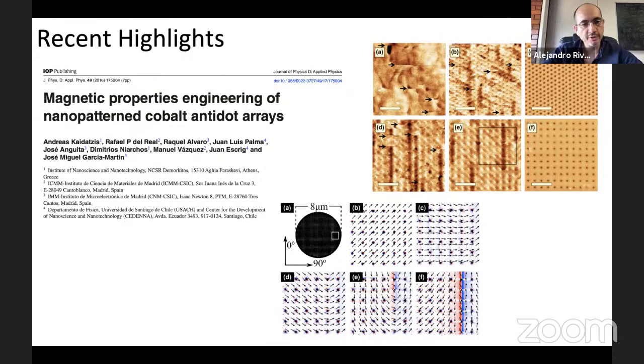As recent highlights, the first work that we want to show is a study in antidot arrays with experimental and simulation analysis. Although this work is not so recent, we want to show it since the computing power for simulation at that moment was a handicap to obtain the whole hysteresis curve in order to complement the experimental study. Indeed, as shown by the MFM image of the antidot array sample, at remanence, there exist superdomain walls, these shaded lines, arranged in different directions. Now, with the computing power of the group, we will be able to obtain the whole hysteresis curve and for different field directions.